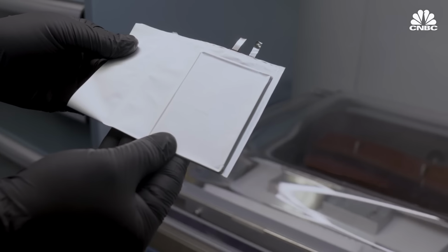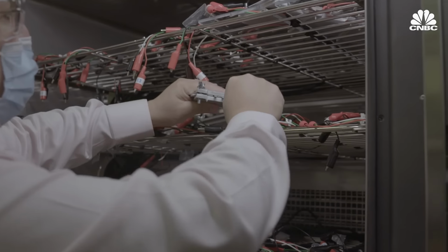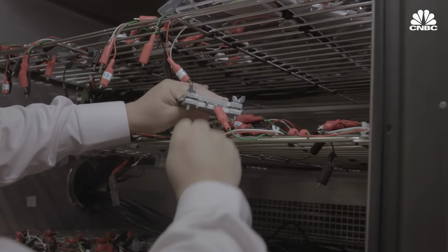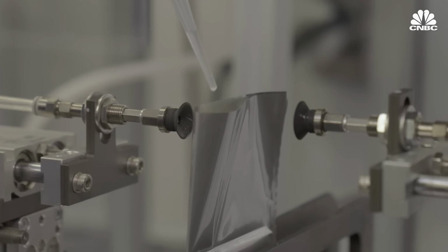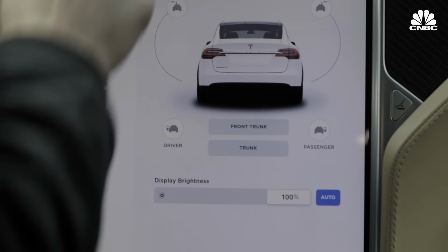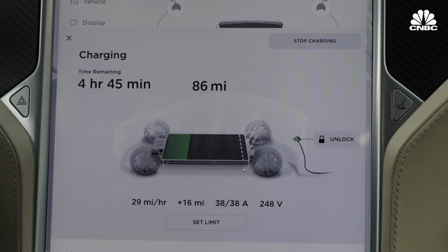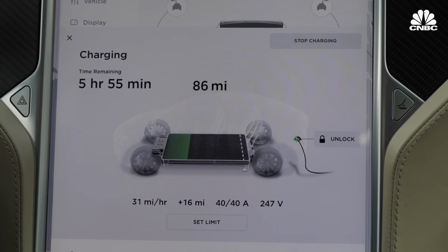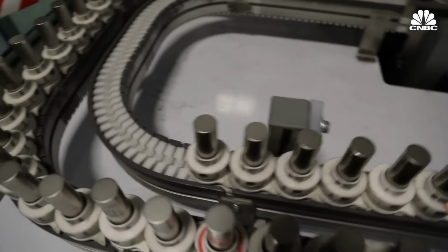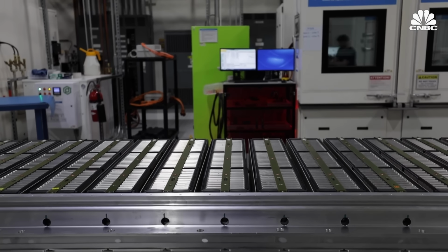The energy density of the cell using our cobalt-free cathode is twice that of the LFP. And in terms of the cost, we're about 30% lower than that of LFPs. Yet at the same time, this cobalt-free cathode meets and exceeds the performance that you would see from a traditional cobalt-carrying cathode in terms of energy density, which is the energy that you can pack in a certain weight or a certain volume. It meets the life expectancy of a traditional lithium-ion battery. And in terms of cost, it's about 35 to 40% lower than the cost of your typical lithium-ion battery.